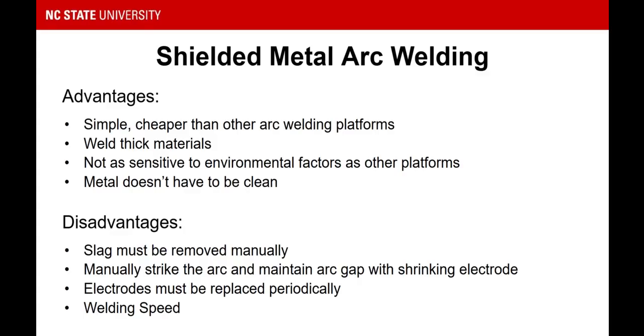They can weld really thick metals, and they can weld thinner metals too, depending on the rod diameter that you use and the amperage that you set the machine at. So they're capable of a wide variety of materials. Another big advantage to stick welding, while you see it used in pipeline and other outdoor environments, is it's not as sensitive to environmental factors as other platforms. TIG welding and MIG welding in particular are very sensitive to wind, and wind blowing that shielding umbrella that I was talking about around and introducing impurities into the weld. Stick welding in particular has always been one of the top processes for using outside when welding, and that's why a lot of folks prefer that in the field.